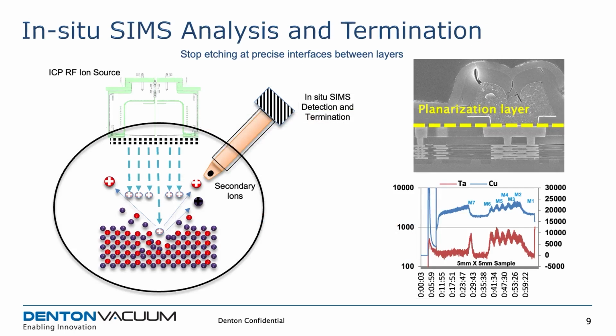So this tool is equipped with a secondary ion mass spectrometer, and it is directed at the center of rotation of the substrate. So as it goes around, and also as the tilt changes, it can still pick up ions that are being etched. And the purpose of this is to produce a chart, as you can see in the bottom right. So the copper is shown in blue. So as we etch through the material, the copper of M7 is high, it goes low. Then we can pick out M6, 5, 4, 3, 2, and then M1 is less visible as you get to the bottom of the chip.